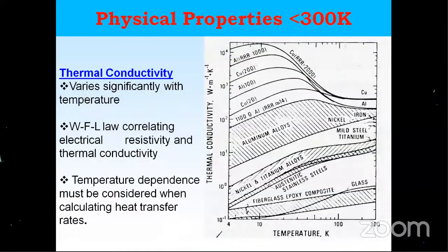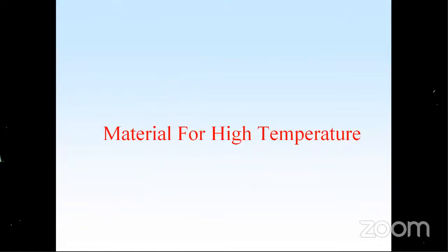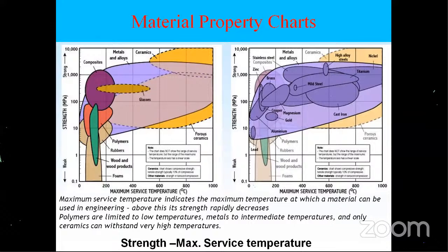Then thermal conductivity for high RRR value increases at low temperature. In most of the alloys it falls down. We have a relation between electrical resistivity and thermal conductivity, known as the Wiedemann-Franz law. Then that's about how you select a cryogenic material. We go for impact testing and use the room temperature YS and UTS values for the part design. For high temperature, it is very interesting because we are storing the propellants and firing, so many materials are exposed to high temperature.